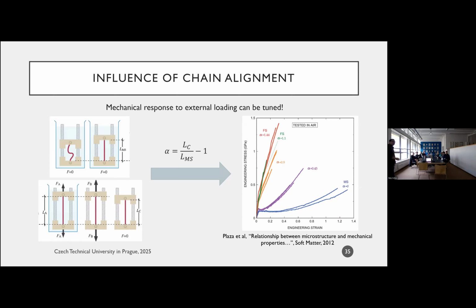And so again, I want to remind you of this experiment that we saw in the first slide before I go into how we model this. This is one of the experiments that led me to start thinking about this problem. What people have done here is they found a post-processing that you could do to a silk fiber. If I have a silk fiber, I put it in water, I let it supercontract, then I dehydrate it under tension.